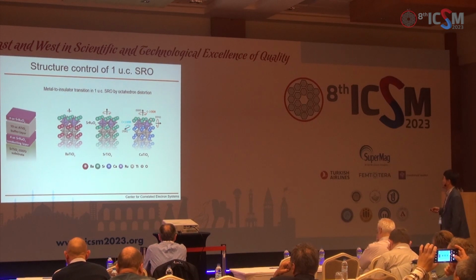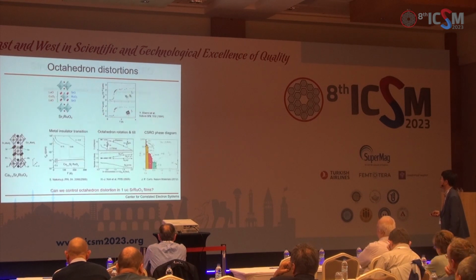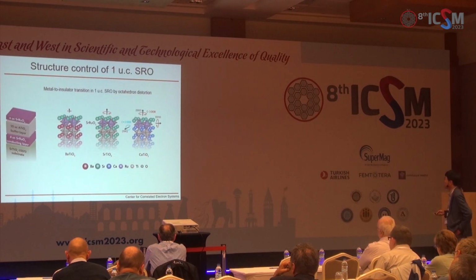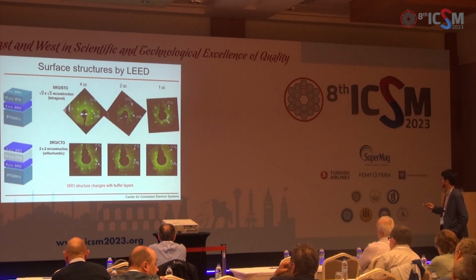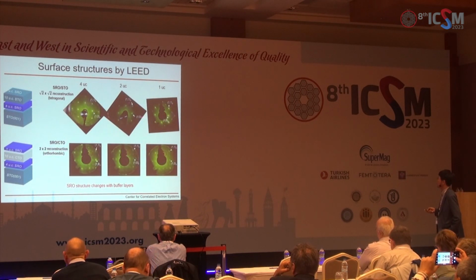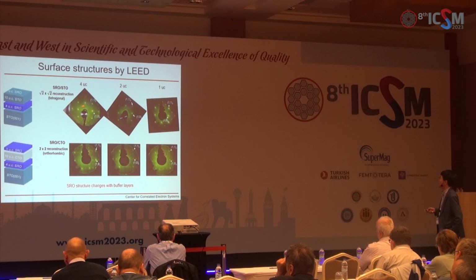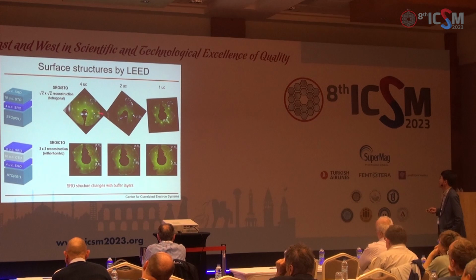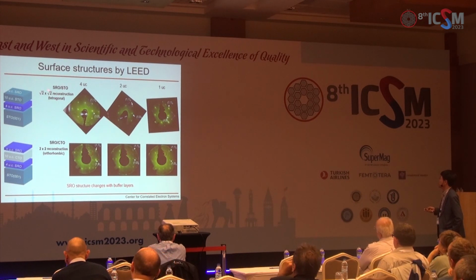So this is basically what we do. This is very similar to what's happening here in this CSR system. To check whether this strontium ruthenate really follows the distortion that I described, we grew strontium ruthenate on STO and strontium ruthenate on CTO, and did LEED measurements here. We found out that this strontium ruthenate grown on STO has a root 2 by root 2 reconstruction.